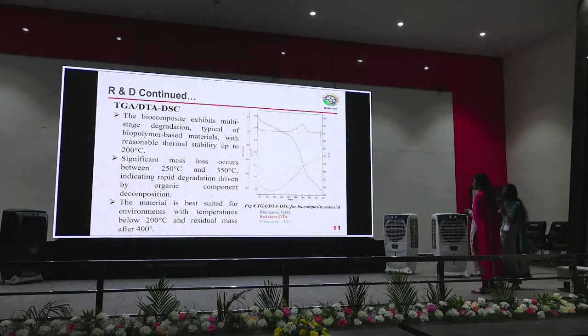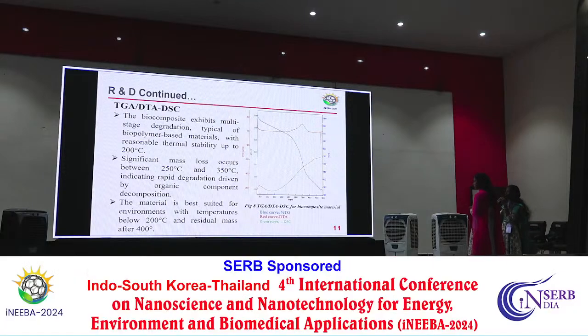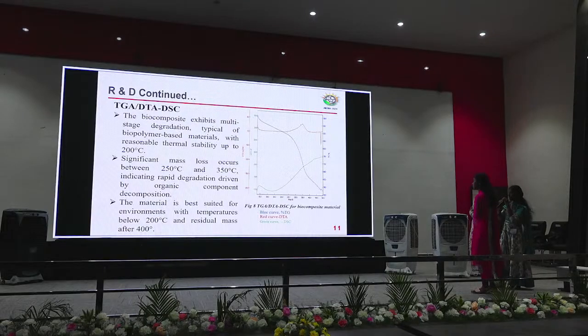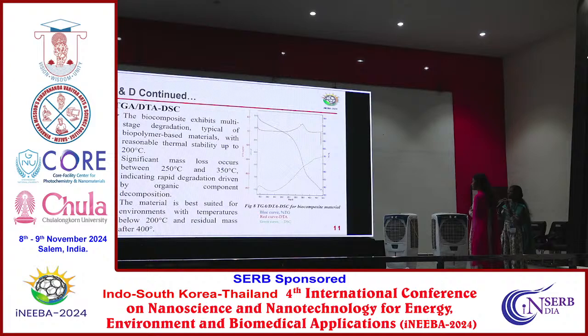Then from 200 to 400 degrees Celsius, the mass loss increases because of the presence of organic material. Above 400 degrees Celsius, the mass loss is reduced because of inorganic thermal residue materials. In DTA, represented by the red curve, the decomposition rate takes place between 250 and 350 degrees Celsius. The maximum decomposition takes place at 300 degrees Celsius. Later it is reduced.